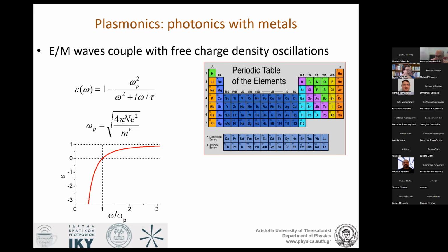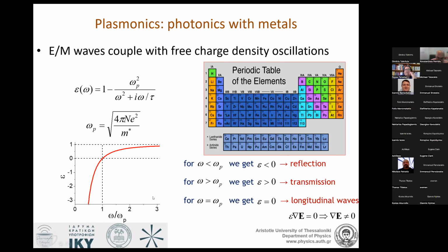It does not coincide with the maximum of the plasmonic effect, but indicates the spectral range where we would expect it, with a deviation of a few nanometers or a few tens of nanometers if we are working in the visible and UV range. So for the metals, for frequencies less than this plasma frequency, we have a very high reflection. For frequencies higher than the plasma frequency, we have mostly transmission. So it's like the metal material or the conductor material becoming a transparent material. And exactly at the plasma frequency, we have longitudinal waves of the electrons in the material, in the conductor.